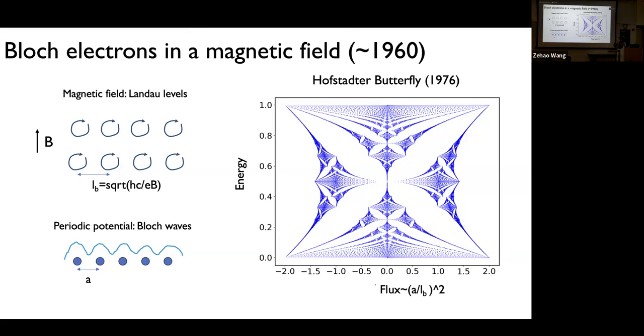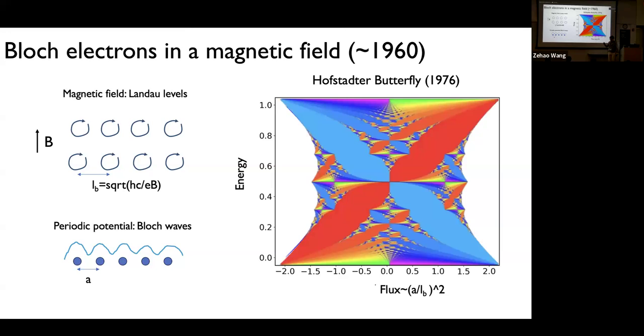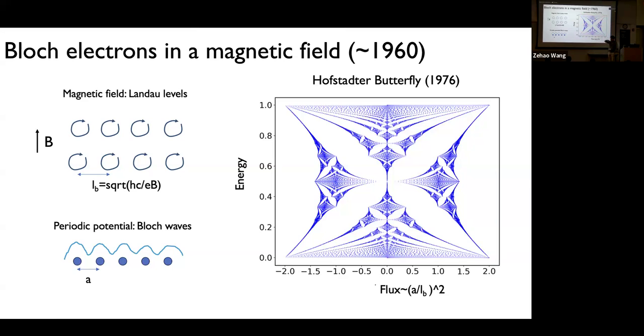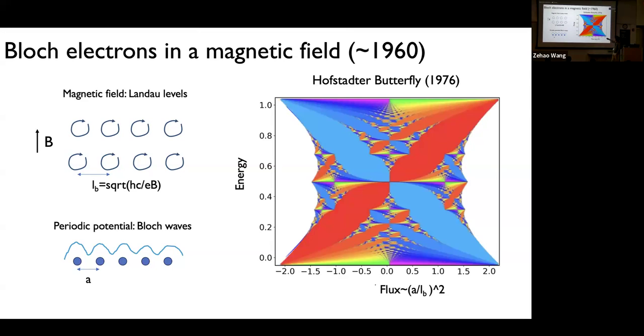And now going back to the Chern band, what's remarkable, and the reason why this attracted so much attention in the community, is that if you compute the Chern number of this spectrum, you can actually color the spectrum. Whenever you have a gap, whenever you have an empty space, you compute the total Chern number of all the filled bands. And what you will find is that they're all very colorful. What that means is that if you are able to position yourself in any of these empty spaces, then you actually have a Chern insulator in some sense. But again, it's a little bit of Landau level physics mixed with Bloch wave function. But this is already a very good starting point, at least at that time.